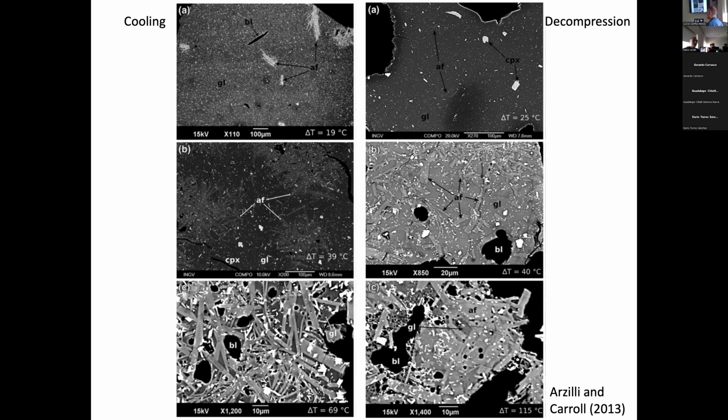And therefore, when you take the length, you have to divide by time. The time is the duration of the experiment. So taking the larger crystals means that possibly you take the crystals that nucleated at the beginning of the experiment. So dividing the length by the time, you have the growth rate. The assumption is that the smallest crystals possibly nucleated later. You see that it's more complex than that.